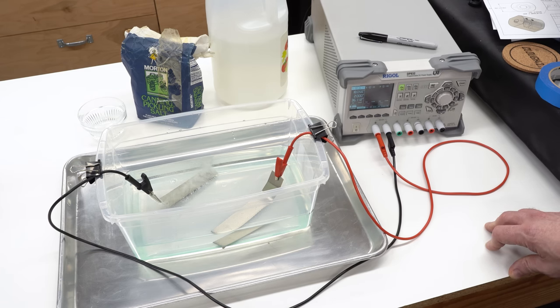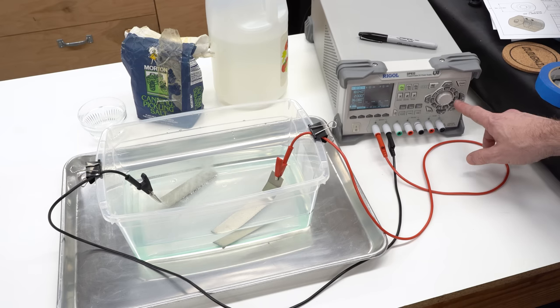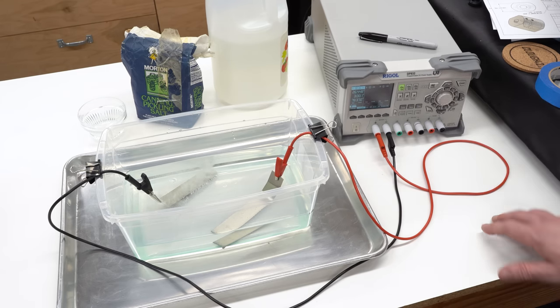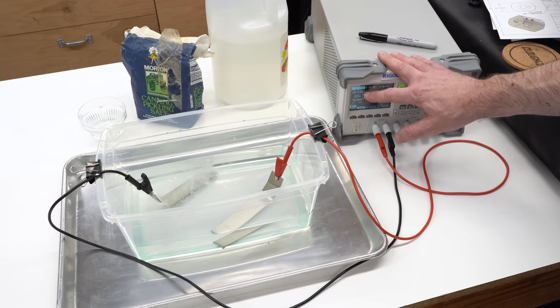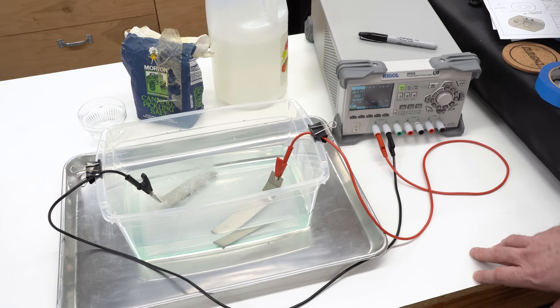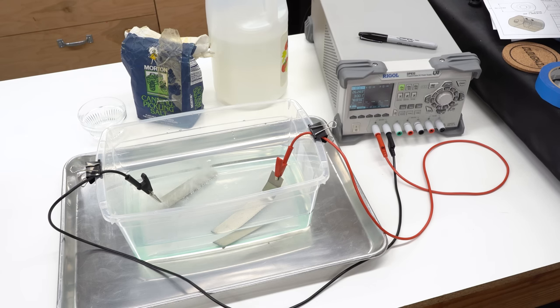Nothing's exploded yet. Let's try three amps. That's the maximum this power supply can run on one channel. Looks okay. I think I'll just let this run for a while and we'll see what we get. We're running three amps at about 26 volts. And again, the power supply is adjusting the voltage to get the current that I asked for.